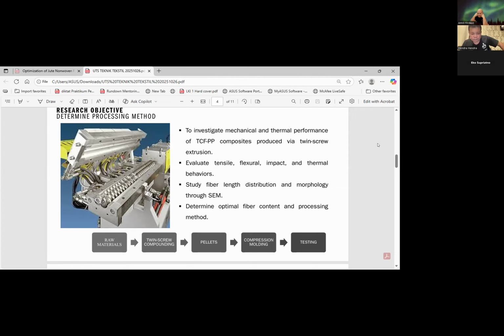They then examined several aspects. First is mechanical properties, including tensile strength, flexural strength, and impact resistance. And then the thermal properties using TGA and DMA, dynamic mechanical analysis, and also the morphology through scanning electron microscopy, or SEM, to observe how the fibers are distributed and bonded inside the matrix. And finally, fiber length distribution, since the fiber can be shortened by abrasion or breakage a little bit. So processing can strongly affect the performance.